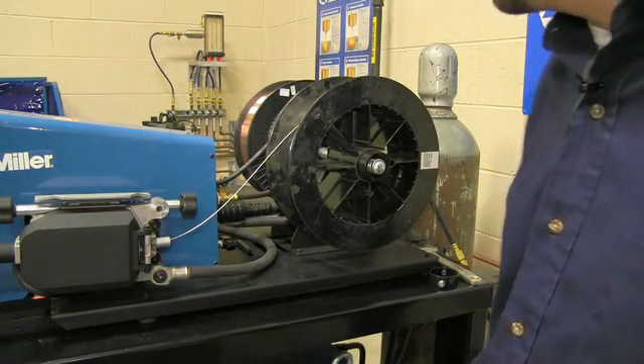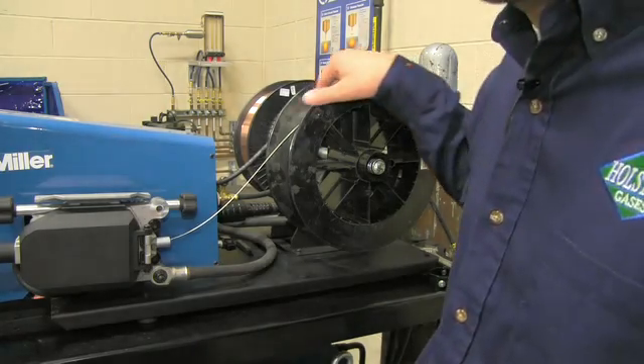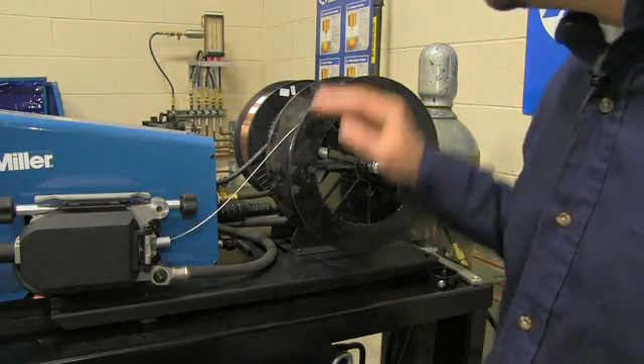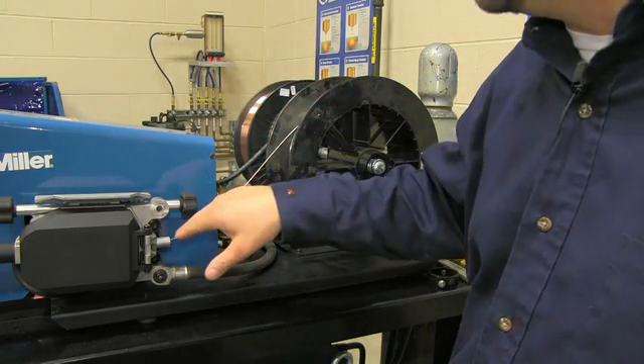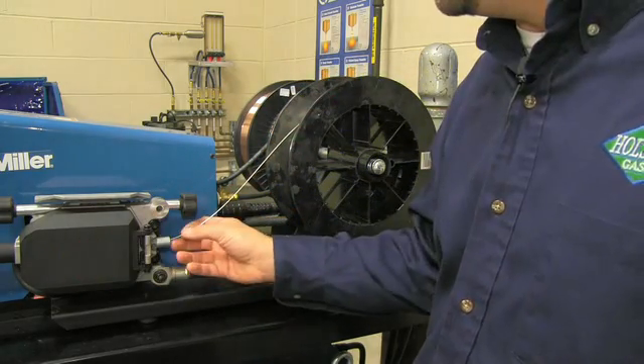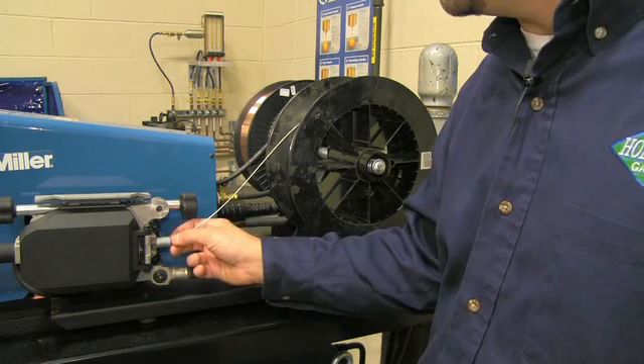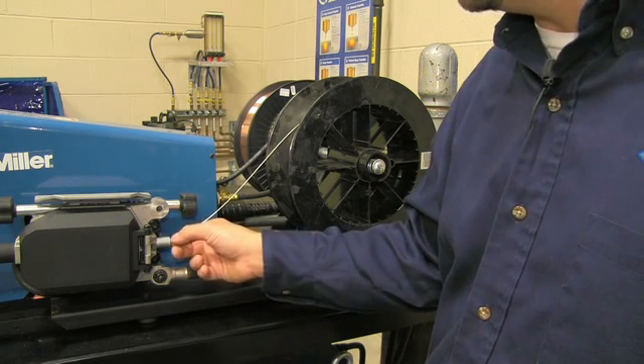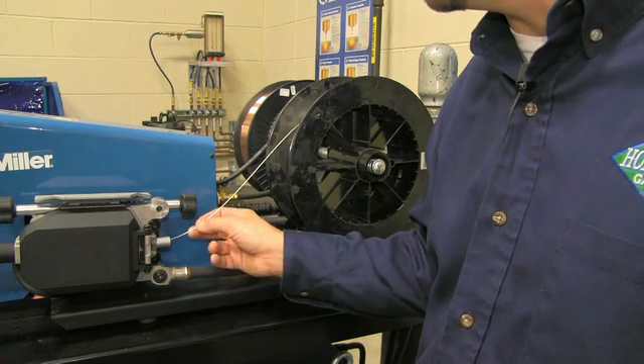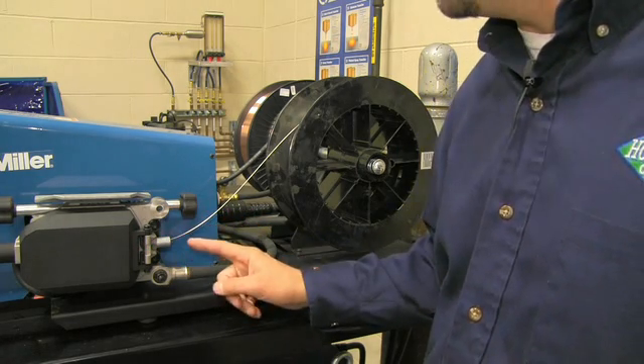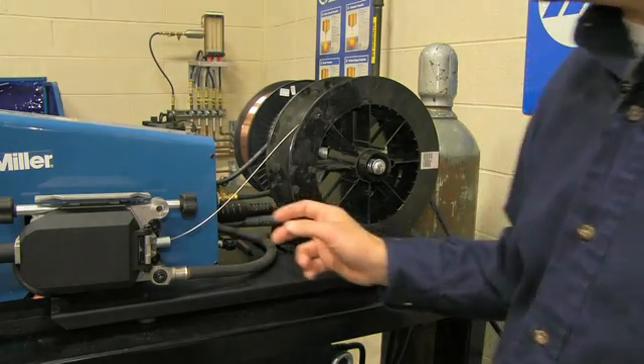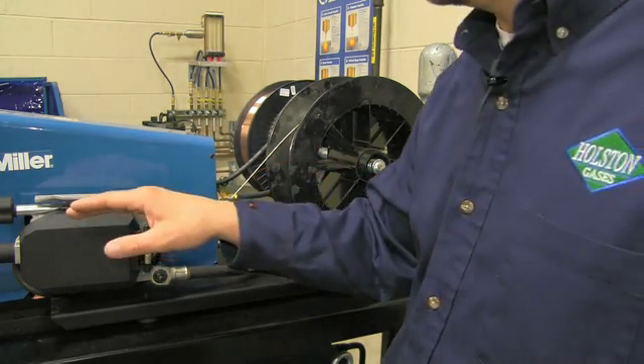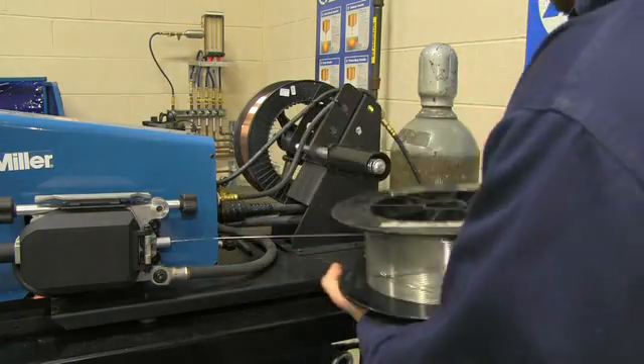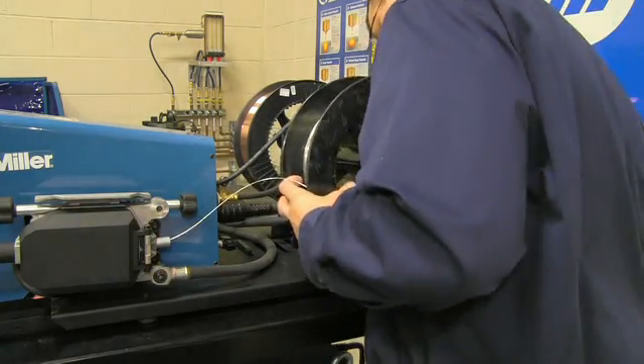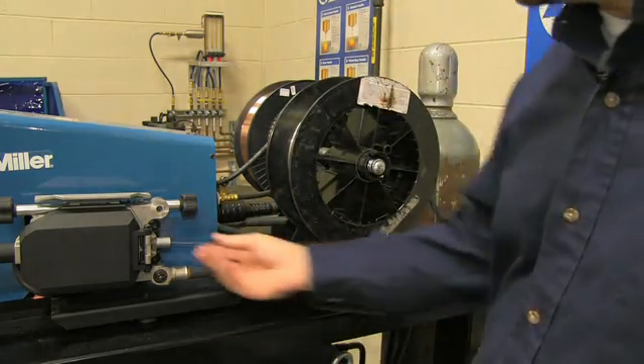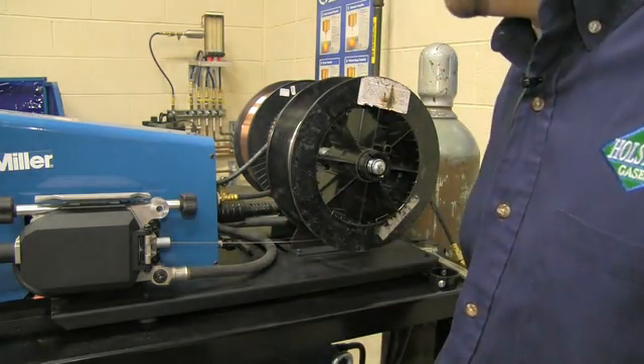So something else to consider when installing the spool of wire is the direction at which the wire is going to unravel or come off of the spool. As you can see here, the wire is coming off at about a 45 degree angle, but the wire drive housing in the inlet guide is sitting straight at 180 degrees. So this causes an area where the wire is going to have to make a pretty harsh bend to be accepted in the wire drive housing, and this is going to cause excessive wear on the inlet guide and also is going to cause some poor feeding. So the proper way to do it is, if the wire drive assembly is in this position right here, to flip the spool over and install it to where it comes off in a straight line. That's the correct way to install the spool of wire.